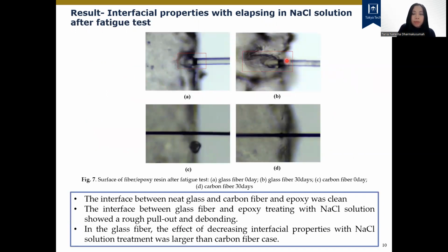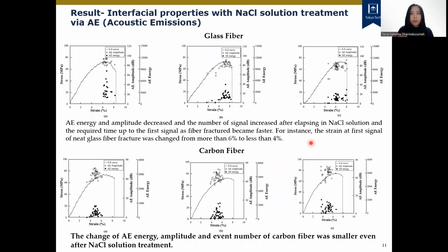And also we can see from this figure, this is also to know about the interfacial properties. We can see that the interface between carbon fiber and epoxy is actually clean. But the interface between glass fiber and epoxy after NaCl solution treatment shows a rough pull-out debonding. So in the glass fiber, the effect of decreasing interfacial properties with NaCl solution treatment was larger than in the carbon fiber case. Okay, and this is interfacial properties using acoustic emission, a non-destructive test. We can conclude from the result that the change of acoustic emission energy, amplitude, and event number of carbon fiber was smaller even after an NaCl solution treatment.